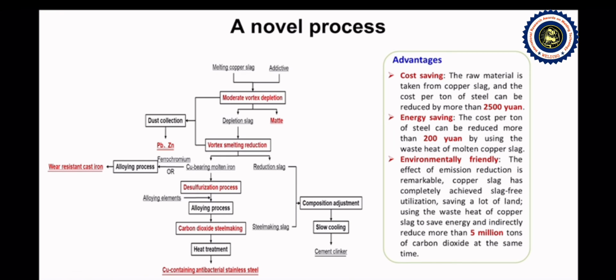This process has many advantages. The raw material is taken from copper slag, and the cost per ton of steel can be reduced by more than 2,500 yuan. The cost per ton of steel can be reduced by more than 200 yuan by using the waste heat of molten copper slag. The effect of emission reduction is remarkable. Copper slag has completely achieved slag-free utilization, saving a lot of land, using the waste heat of copper slag to save energy and indirectly reduce more than 5 million tons of carbon dioxide at the same time.